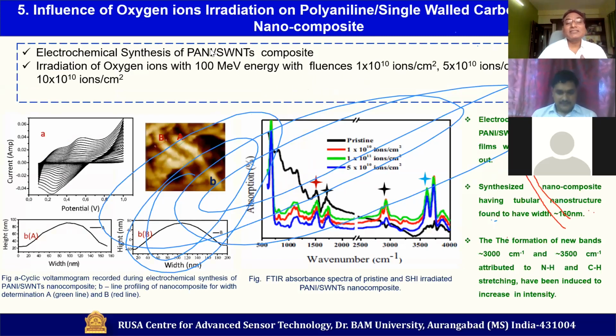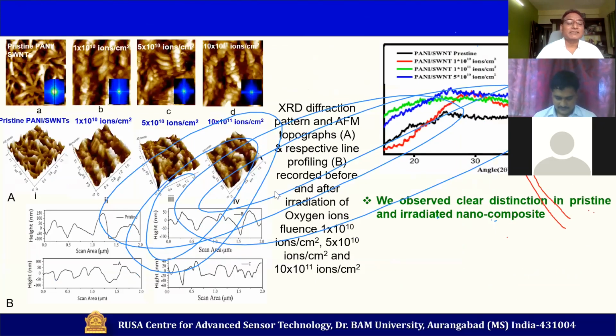So what we did, this same structure, polyaniline with SWNT, we exposed it to SHI irradiation, oxygen ion, with different fluences, and we investigated this as well. This is the CV while synthesis. This is AFM, and then with different fluences, we can see this is the FTIR, and a clear-cut distinction in the FTIR spectrum as well. These are AFM images after SHI exposure of various fluences.